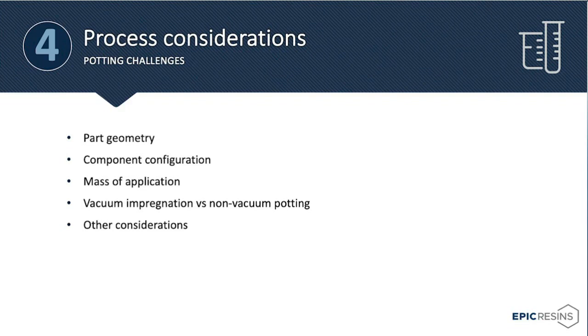Cure time is the amount of time it takes for a material to reach greater than 95% cured. Many people will confuse this with handleable time. In many cases, a material can be handled and moved on to its next portion of the manufacturing process before the cure time is complete. Another process consideration is potting challenges. For example, part geometry, component configuration, mass of the application, vacuum impregnation versus non-vacuum potting, and other considerations.